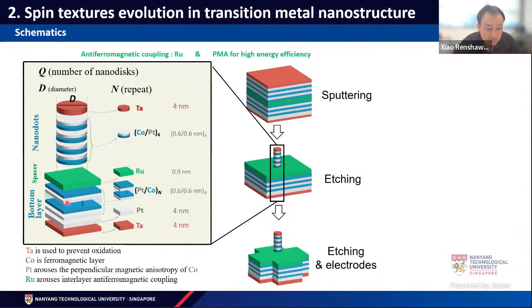So on the bottom, we have a repeated cobalt platinum structure. Then in between, there's a ruthenium antiferromagnetic spacer. On top of that, there's also a PMA, perpendicular magnetic cobalt platinum. On top, there's also a tantalum layer, because that layer can protect the sample from oxidation. Basically, it's a protection layer.